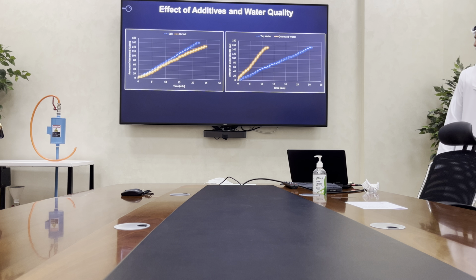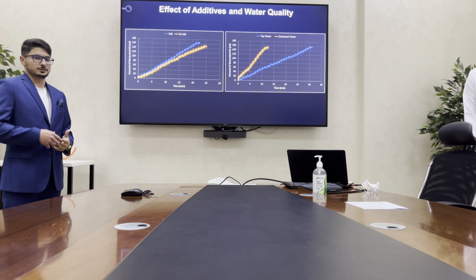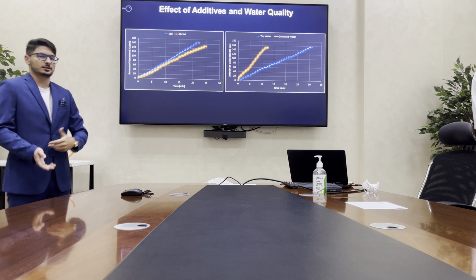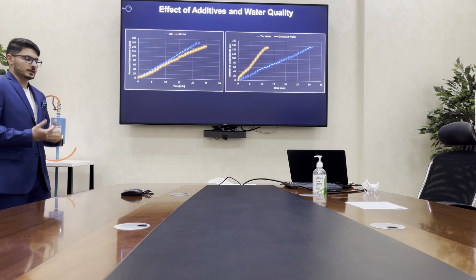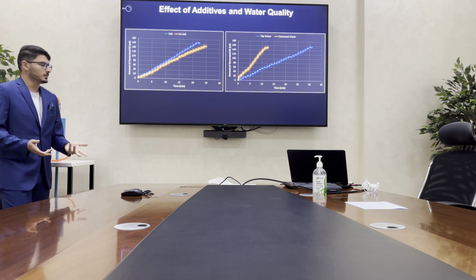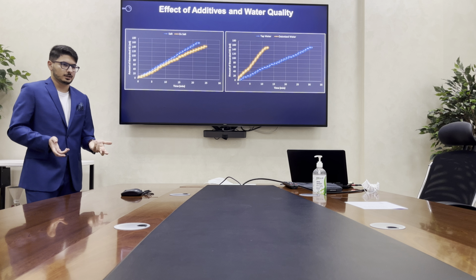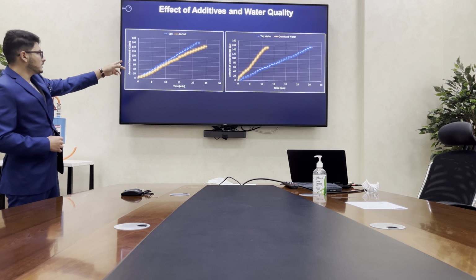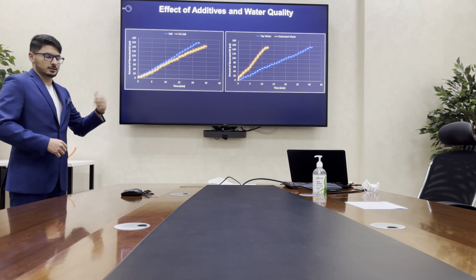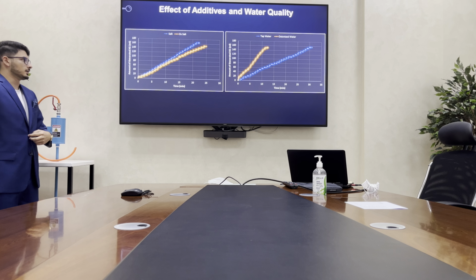We also discovered the effects of salt. Note that in literature we have seen trends of mechanical treatments such as planetary ball milling. In this experiment, we tried to insert the least energy addition to the system. So we did not add any mechanical treatment, only grinding the salt, which was only commercial sea salt. The salt was a mixture of salts, but mainly comprising of NaCl.